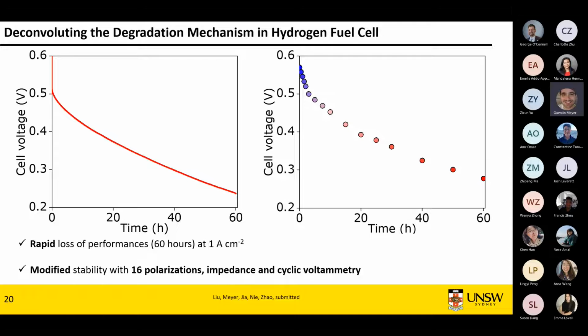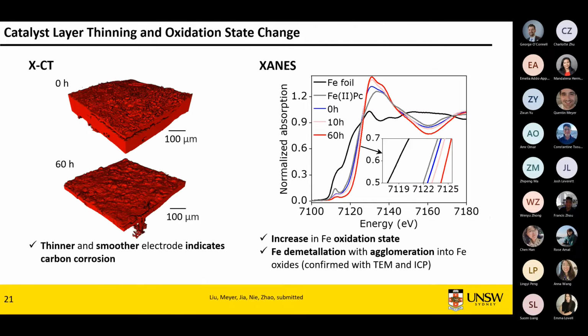We also designed an experiment where we captured basically polarization curves, impedance, and CVs at different stages to try to understand what's happening. And basically, when we take a measurement, it's like we're freezing the state of the cell. We take a quick polarization curve, quick impedance, then we carry on the stability. We're pretty confident that it's not impacting things too much because it's overall looking very similar to a continuous degradation. So before we did all that, we actually tried to do some operando measurements.